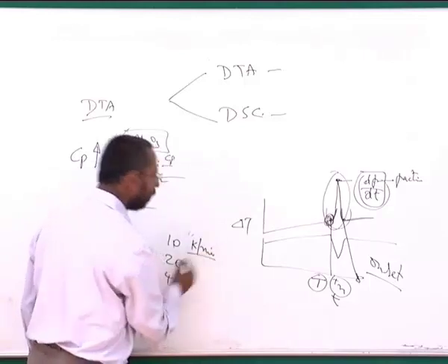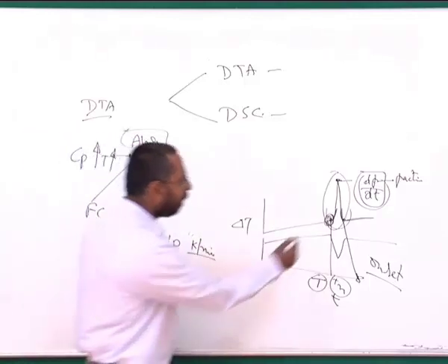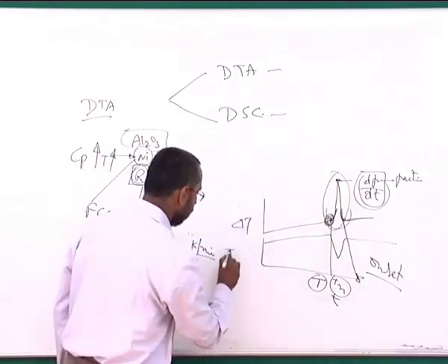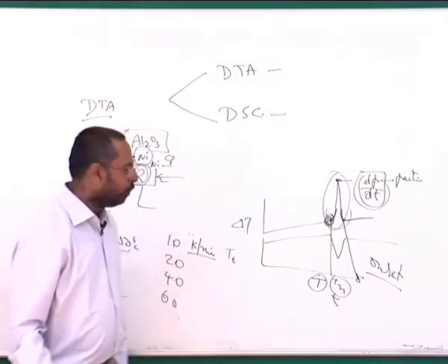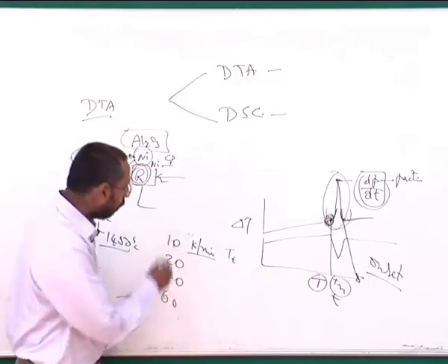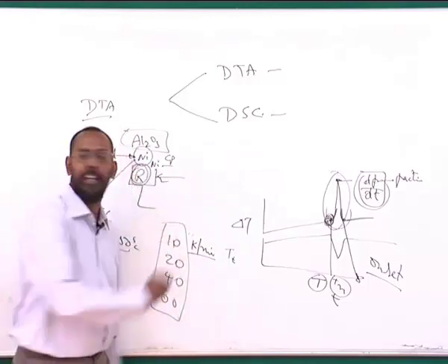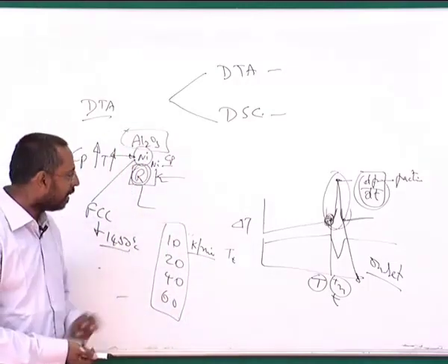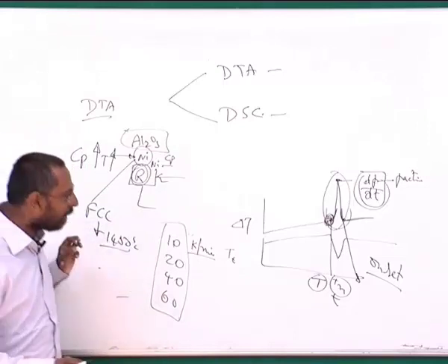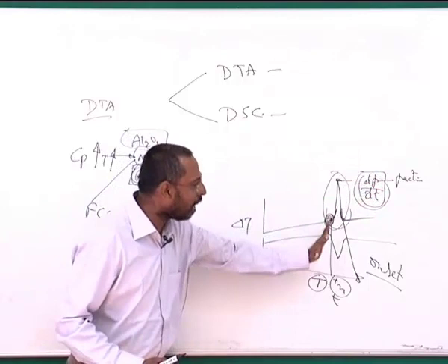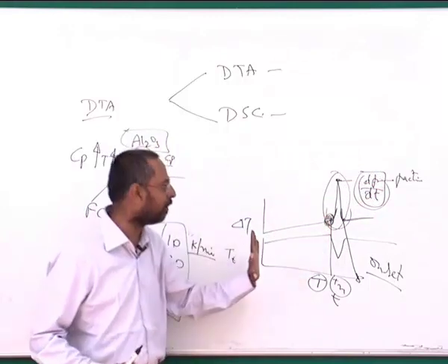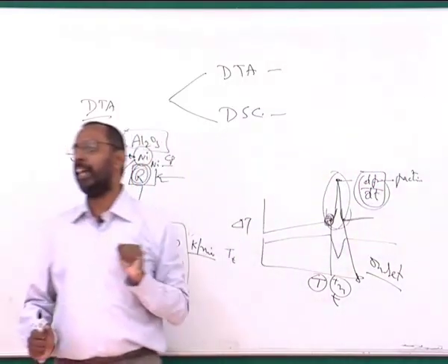And at each of these particular heating rates, I measure the onset temperature, which I call the temperature of transformation. You will see that the temperature of transformation will not be the same for different heating rates. The reason is there is an inertia in the system. As I am heating very fast, instead of the transformation starting at the equilibrium transformation temperature, it starts at a temperature higher than that.